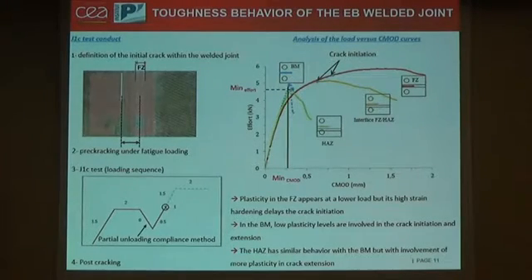Toughness tests were conducted on conventional compact tension specimens with different positions of the notch radius, of the mechanical notch. In the first approach, we compare the evolution of the effort as a function of the crack mouth opening displacement for 4 selected tests. First of all, we have the fusion zone in red. As we can see, plasticity appears at lower loads, but its high strain hardening effect delays the crack initiation.